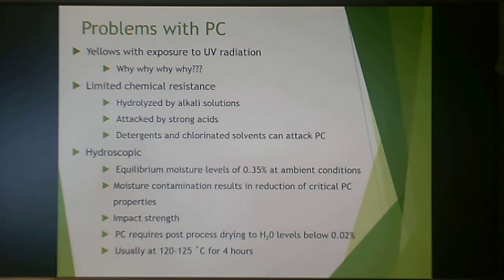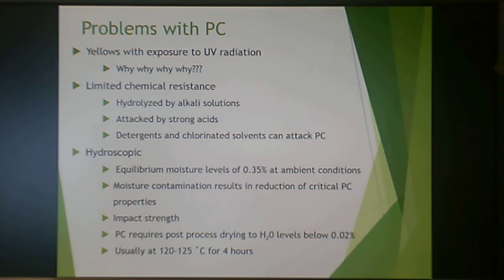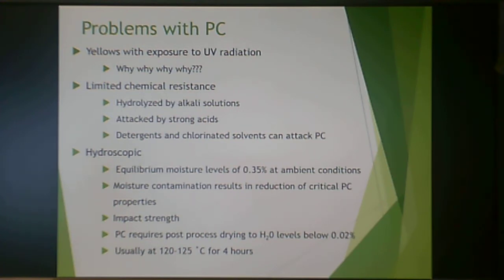Another significant problem is that polycarbonate is hygroscopic, absorbing about 0.35% equilibrium moisture at ambient conditions. Although this seems low, it is enough to cause contamination that makes final product properties unpredictable. Moisture acts as a plasticizer and reduces mechanical properties, including impact strength. You must dry the material at 120 to 125°C for about four hours and use it immediately after drying, keeping moisture levels low throughout processing.